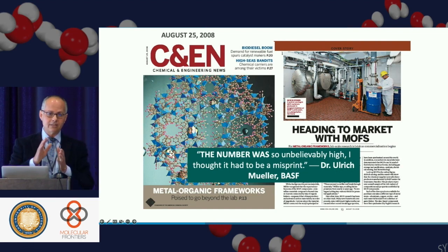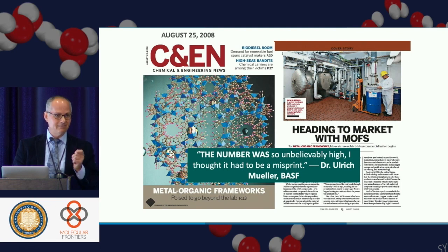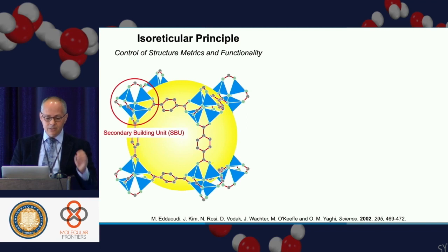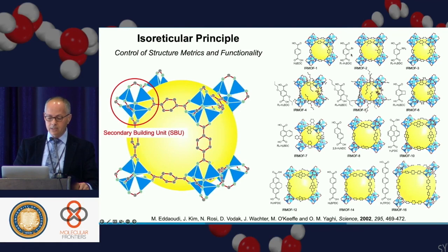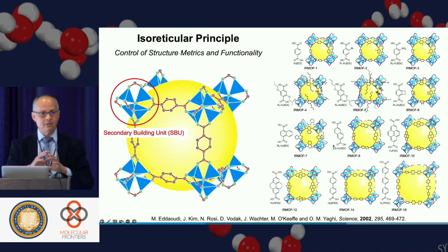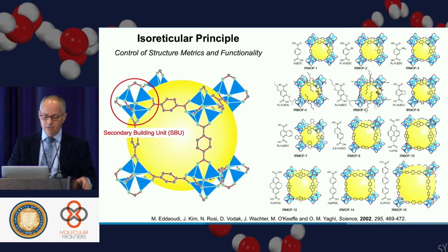So my talk is divided, I neglected to mention, roughly in half: half of it is about materials and how we were successful in making and crystallizing them. And the other half is how that makes them extremely powerful materials, because they are crystalline, to harvest water from desert air. Okay, so that's what I wanted to say. But once you know the conditions under which this basic zinc acetate corner or junction results, then you could use the same reaction conditions to use linkers that are functionalized or expanded. And therefore, now you could make materials for the first time where the pores could be functionalized and fashioned for a specific application, or they could be expanded to be able to bind progressively larger and larger molecules.